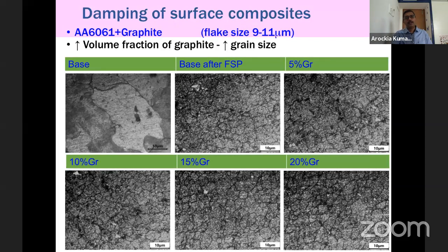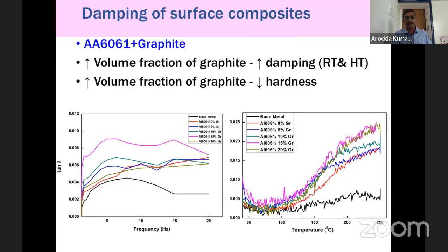So we have also produced 6061 graphite composite. And here, what I'm showing is how the damping property increases after doing FSP with respect to frequency. The y-axis in both the plots is damping. In the first plot, the x-axis is frequency. That is, when I change the loading frequency, what happens to the damping of the material before and after FSP. And when I change the temperature, what happens to the damping before and after FSP.